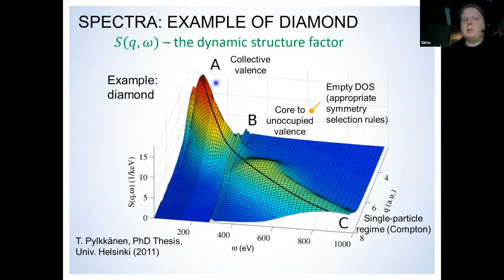So these are typically collective valence electron excitations when we have a condensed matter system. And then this disperses smoothly into Compton line shape at higher momentum transfers, where one probes more single particle excitations. But here in the middle, we have the sharp discrete step, which is now the X-ray Raman line, which is basically due to the core electron excitation. So the carbon 1s core electron has a binding energy of about 300 electron volts. So you see the sharp onset at around 300 eV.